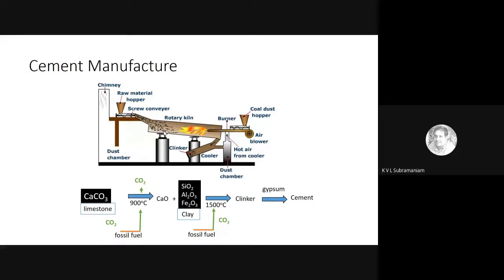But if you look at limestone and I heat it up, it gets calcined. That process is very similar to what we did with the lime mortar. It breaks up into calcium oxide. So I have my calcium, which is the ingredient that I need for making cement. And then I also add clay as my other raw material, and the clay brings in the silica element, the alumina, and the iron element. So these are the three primary elements that come from the clay.